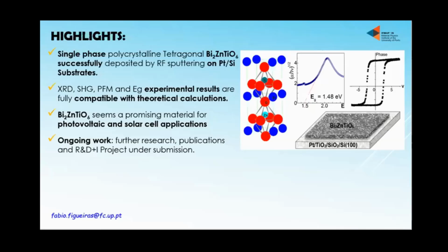Of course, and the transparent substrate, transparent electrodes. But it should be operative on its own. Of course, it can take interlayers between the electrodes and this material to help minimize Schottky barriers and other defects that will happen in the interfaces. And of course, as I was saying, doing a prototype is not so simple as doing the material alone. And having this material alone is already a progress, but the prototype will need other deep studies. Okay, okay. Thank you. Thank you.